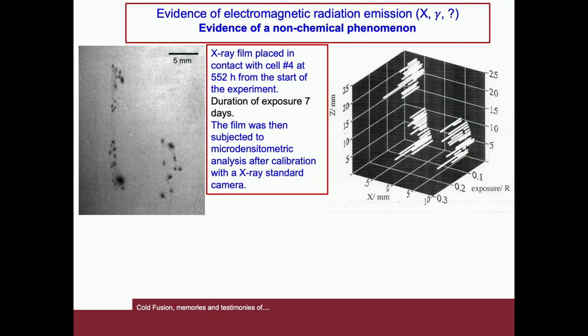Evidence of electromagnetic radiation emission. This is strong evidence of a non-chemical phenomenon. This is the X-ray film that was placed in contact with cell 4 after 552 hours from the beginning of the experiment. The duration of exposition was 7 days.